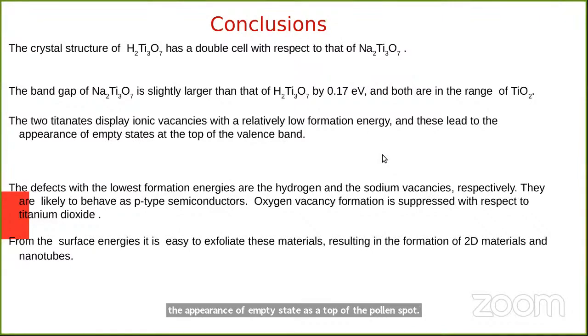The defects with the lowest formation energy are the hydrogen and sodium vacancies. And they are likely to behave as a p-type semiconductor. And oxygen vacancy formation is unfavorable with respect to titanium dioxide. And from the surface energy, we found that it is easy to exfoliate this material to form 2D material and nanotubes.